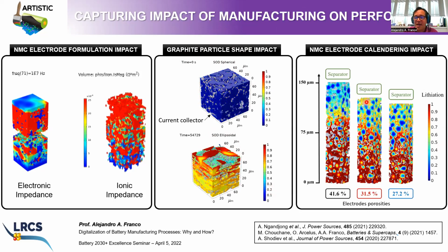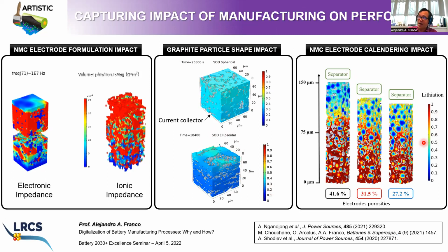And also here you see the predicted impact with this model of the calendering degree on the lithiation, the degree of lithiation at the end of discharge of NMC electrodes, right? You see that the model is capable of capturing the influence of manufacturing parameters on performance, but the beauty of this model is that it can capture this in 3D, in 3 dimensions, right? And also as a function of time.